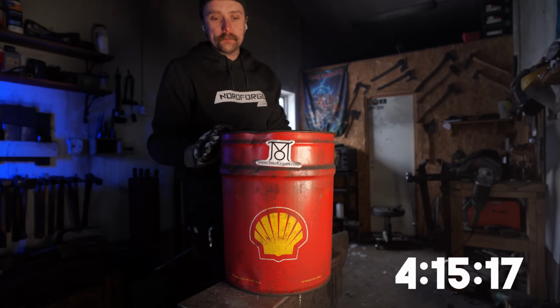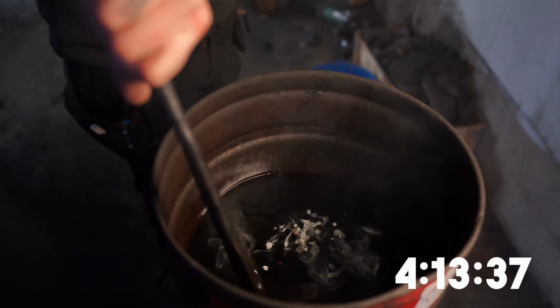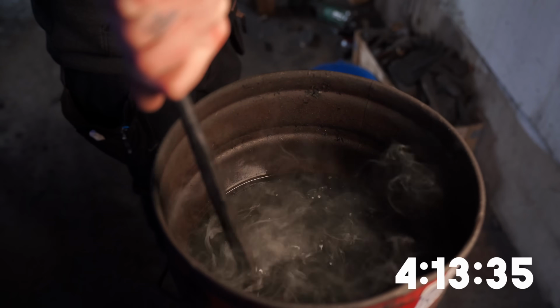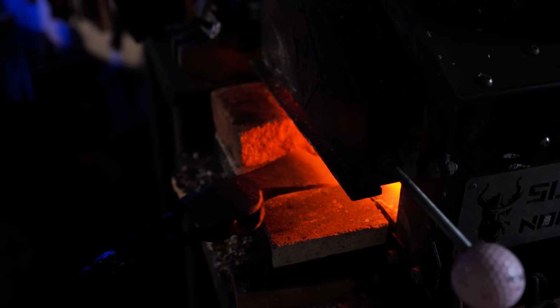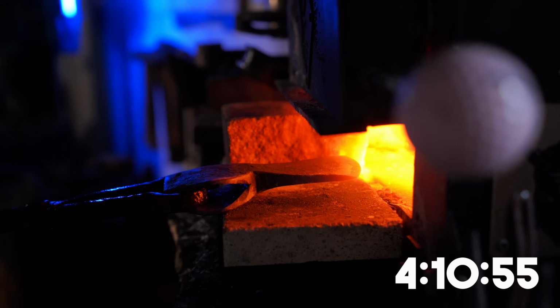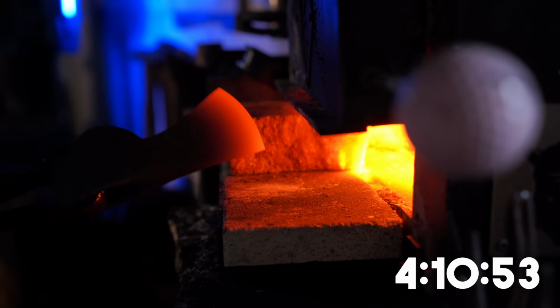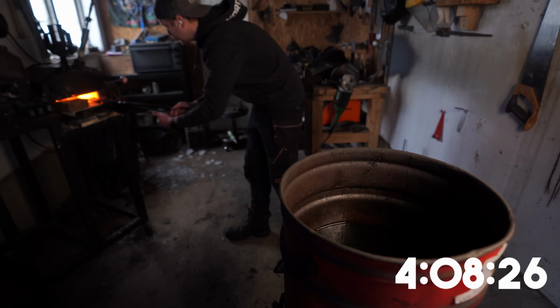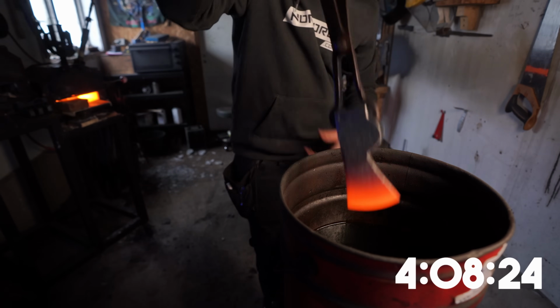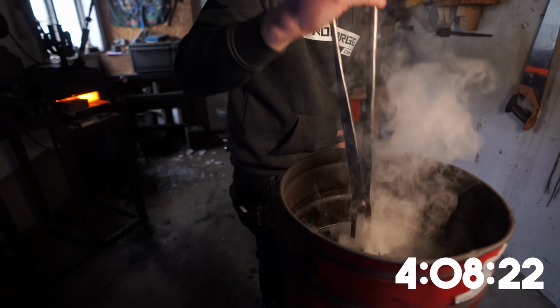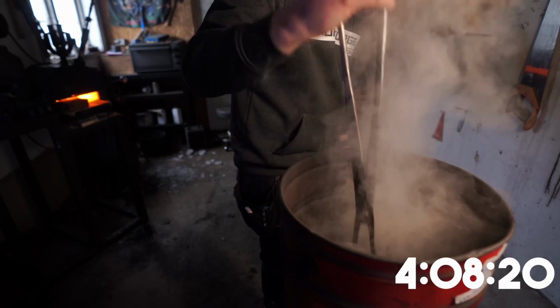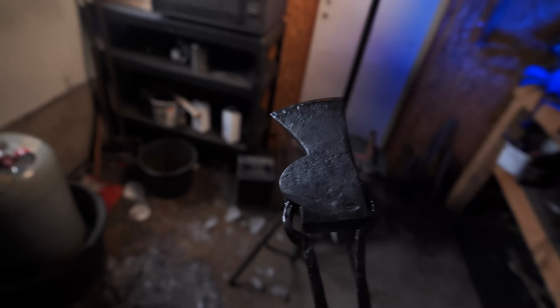It's time to harden the axe, but unlike the 1-hour version, which I quenched in water, this one has a spring steel edge and therefore needs to be quenched in warm oil. So once the oil is preheated, I slowly bring up the edge to temperature and quench it in the oil. After that, I temper it in the oven.